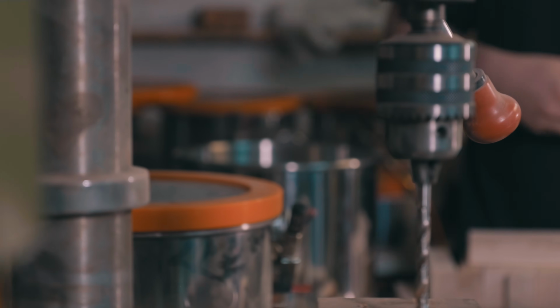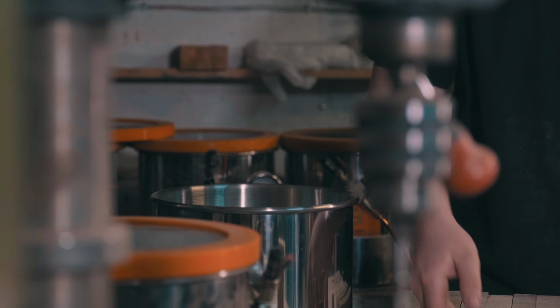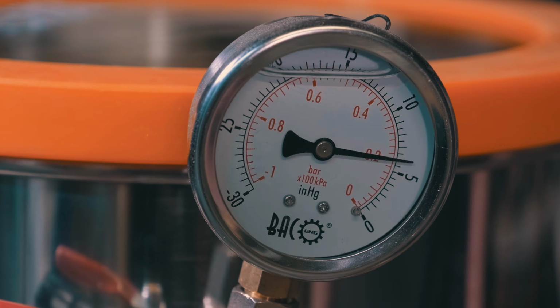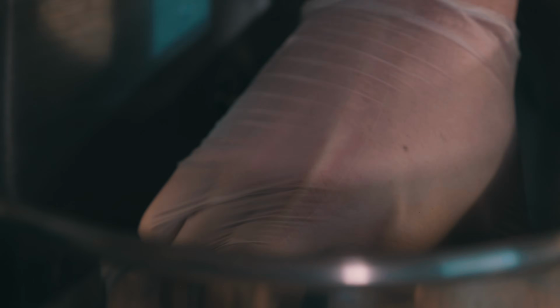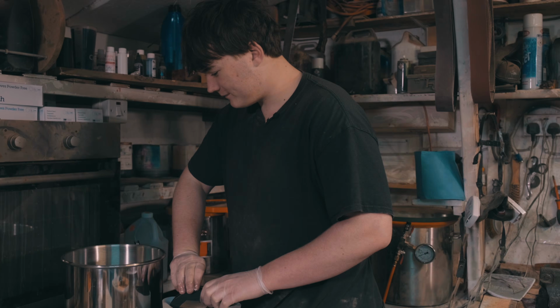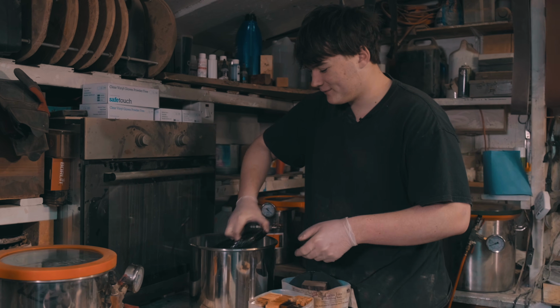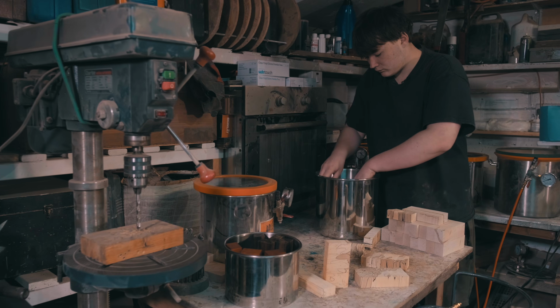So once the wood is dry and in the chamber, I then release the vacuum and put on a weight. Now, this prevents the wood from rising up because it needs to be submerged. If it does rise up, you then start forcing air back into the wood, which is exactly what you don't want. Stabilizing is the process of removing that air and replacing it with resin. So by having a weight on there, we'll keep it all submerged below the resin and preventing any of that from happening. The wood is all in the chamber, weighted down and dry. It's time for the resin.